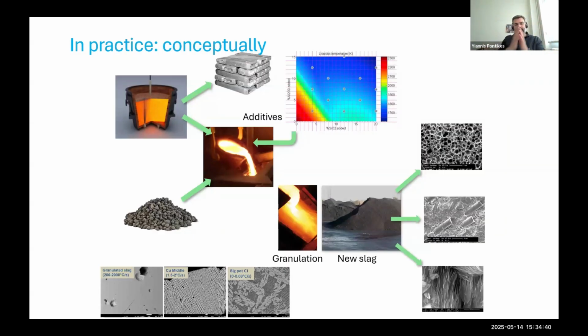So conceptually, now stepping back, nobody wants to mess up this step. This is the money-making element, the metal. So you separate the metal, but you still have a molten slag. Then you think of your additives: calcium, alumina, silica, or anything that makes sense for your process. Ideally, a commodity, so you make a process that is easy for the whole world. You can start from the molten, or you can start from low temperatures and heat it up. Then you granulate. You can do wet granulation. You can also do dry granulation.